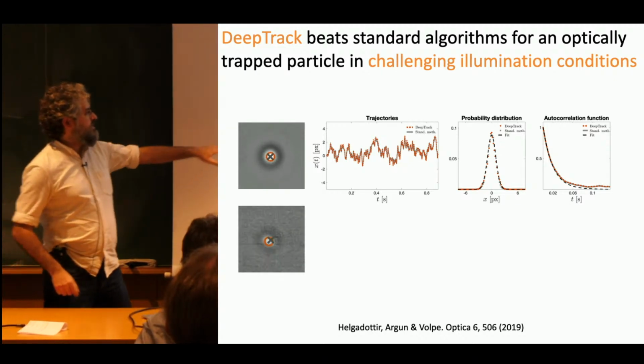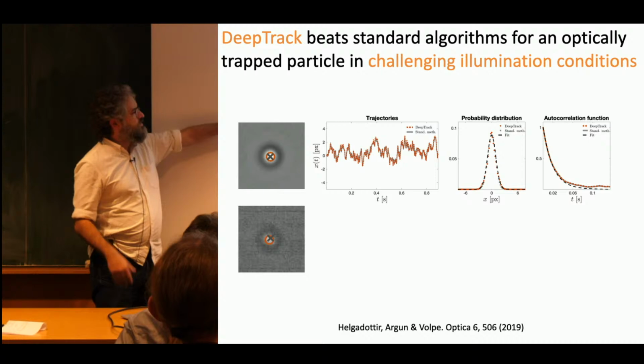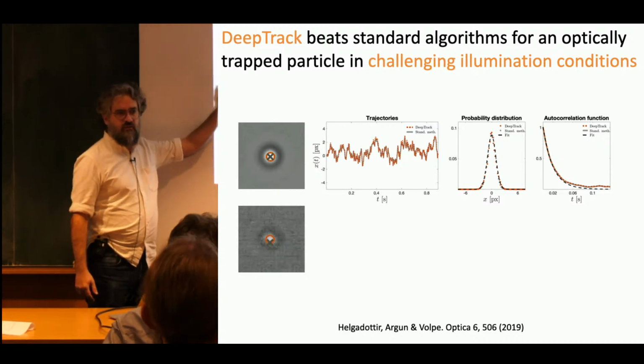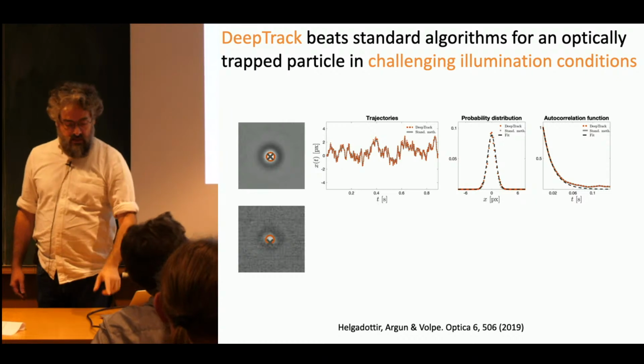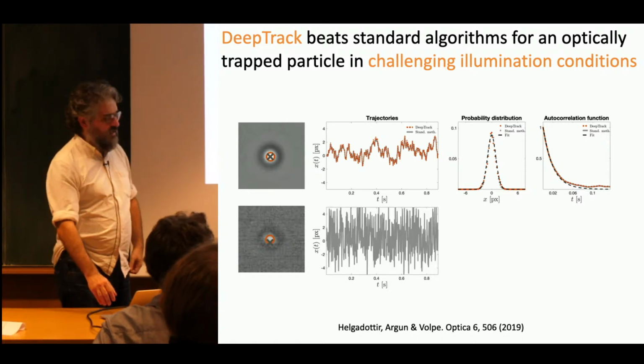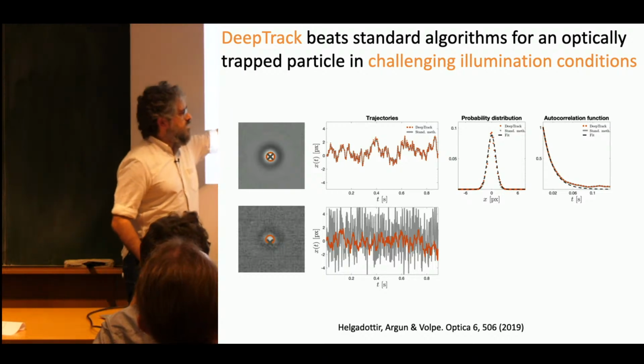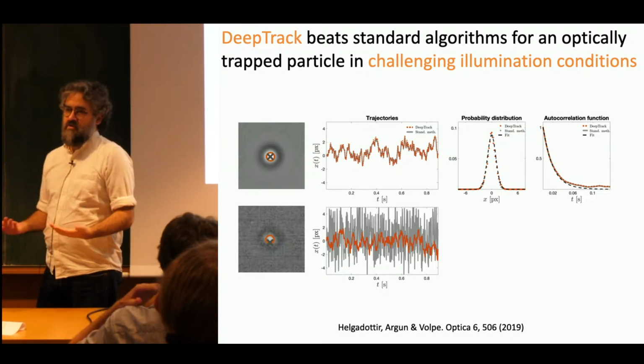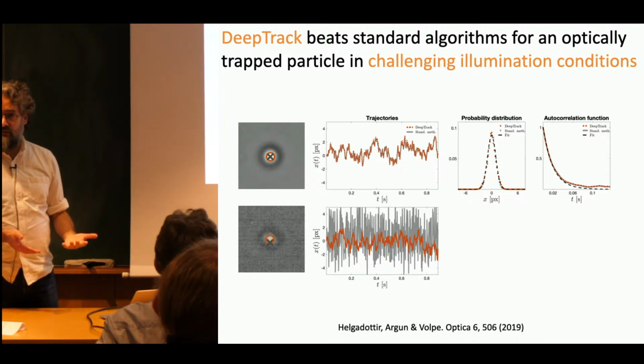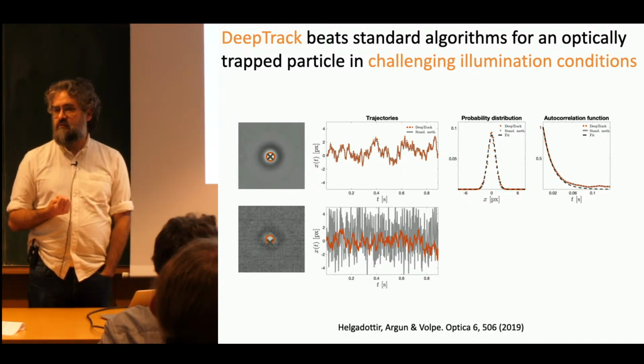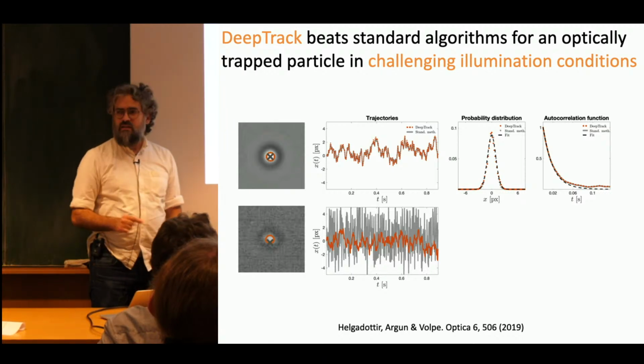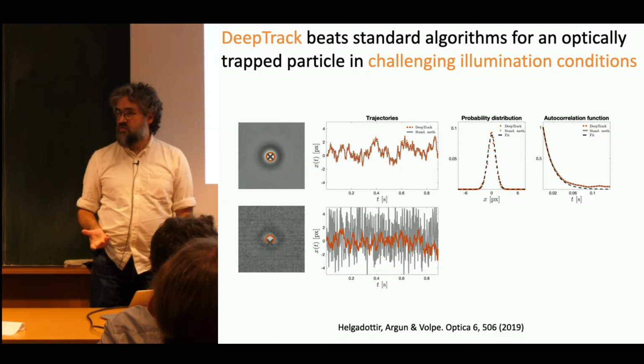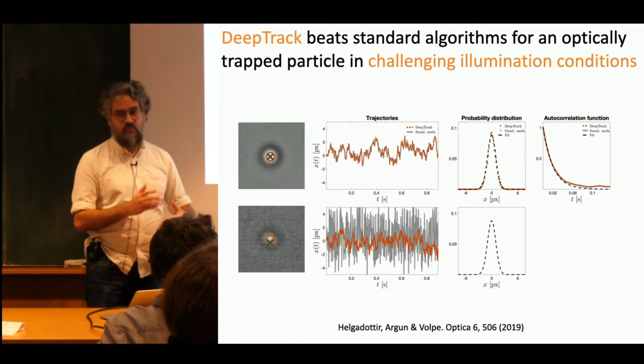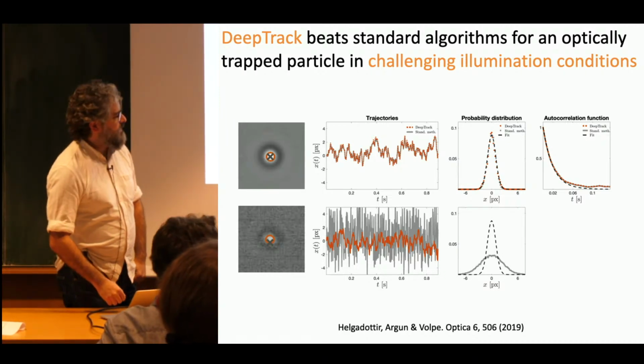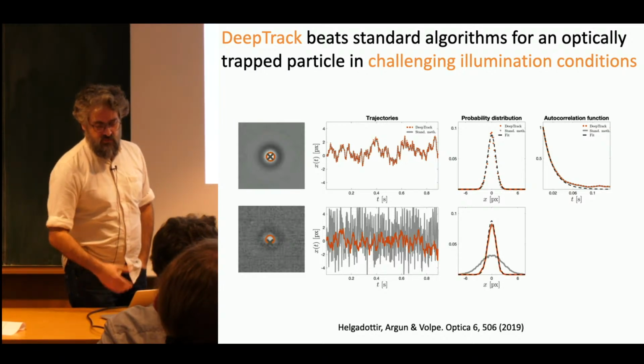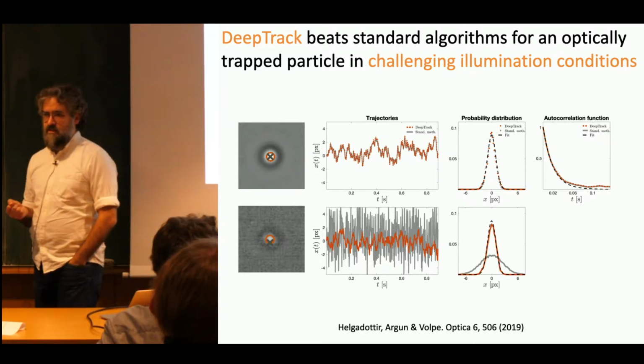Why? Well, because it's an incandescence lamp, so you have oscillations, you have background noise, you have gain noise, you have gradients, you have every possible source of noise. And if you look at the trajectory, this is what we get with the standard algorithm, which is obviously wrong. And this one is what we get with DeepTrack, which seems more reasonable. Of course, it's a random process, so we don't really know what we have to get out of it. But we know what the statistics of the random process are. Since this is the very same particle in the very same trap, we expect it to have the same probability distribution, for example. So we expect that the probability distribution should be this one. Well, what we get with the standard method is something that is clearly wrong, but with DeepTrack we get the right one.